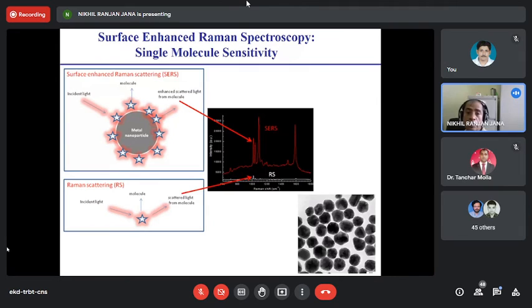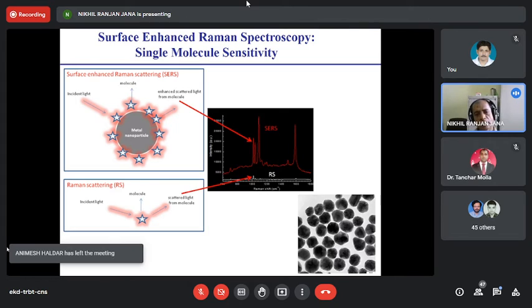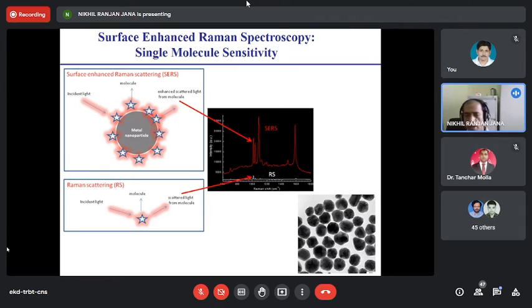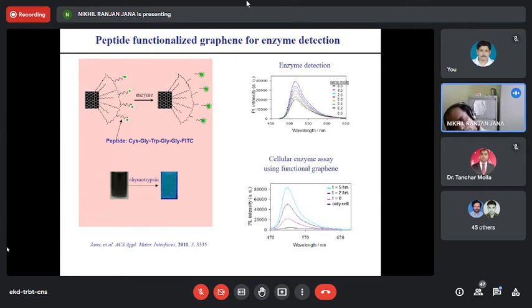Surface enhanced Raman spectroscopy, single molecule detection. Gold and silver nanoparticles are very powerful materials. They have surface plasmons. Their colors are due to surface plasmons, plasmonic electron clouds. These plasmons can be excited by lasers. And any molecules that are adsorbed at the surface of these nanoparticles will experience more electromagnetic field. So Raman signals will get enhanced. Billion-fold enhancement of this Raman signal will lead to single molecule sensitivity. So detection of a single molecule, highly sensitive detection, can be done using gold or silver nanoparticles. This subject is very mature, very intensely studied. This needs several lectures. I'm just giving a brief overview.